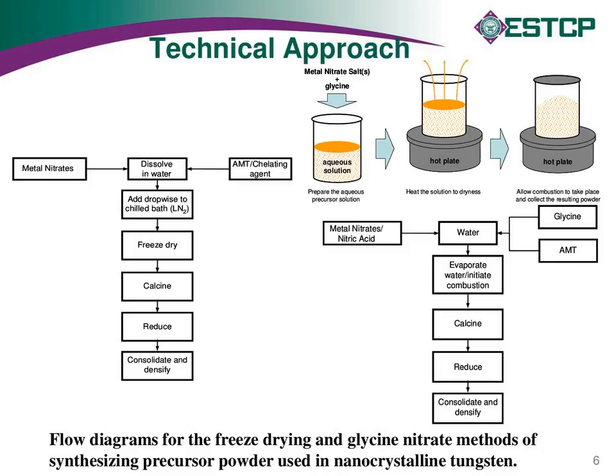to large-scale combustion synthesis. But when we licensed the process to Praxair, and they're no longer Praxair, I've drawn a blank on the name right now, they adapted it, and they ran a variant of the spray drying process with it. So they took the glycine nitrate process and converted it into a continuous spray drying sort of approach. It's very similar to spray drying, but it does go through the combustion. And so in their case, they're doing large quantities. This is a nearly continuous, kilogram per hour type process for producing fine ceramic powders.